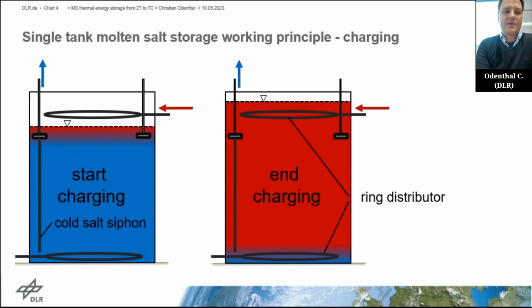And here you see basically the working principle of the system. Okay, so you can extract the cold salt from the bottom with a pump and simultaneously add hot salt at the top through a distributor ring. And then over the course of the time, as you extract the cold salt and add hot molten salt, you end up with this situation that you have the tank completely filled with salt. And what you can also observe in that case is because of the lower density of the hot salt, you will have a higher filling level in the tank after the end of the charging process.